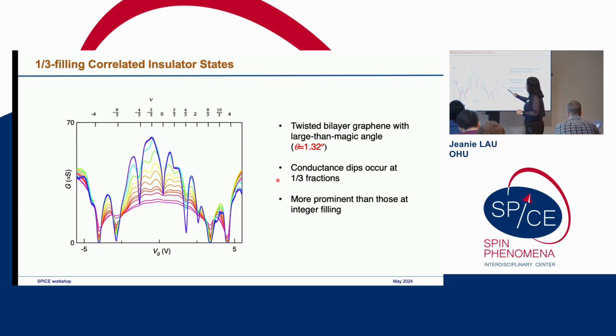At the charge neutrality point we have 0. This is a dip, a peak in resistance, a dip in conductance. Then we have 4 and -4, and these are the band insulators. Now we have very robust insulating states here, at plus minus 8/3 and plus minus 4/3. These are these peaks. On top of that we have features at 2/3, I think there are some features here, and 10/3.